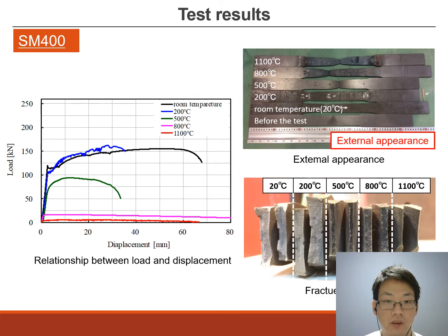This slide shows the result of high-temperature tensile tests. First of all, the SM400. SM400 means the minimum tensile strength of carbon steel is 400 Newton per square millimeter. The relationship between load and displacement shows that the load decreases as the temperature increases. As can be seen from this figure, there is a tendency for the carbon steel to fracture at 200 degrees, which is called blue heat embrittlement.